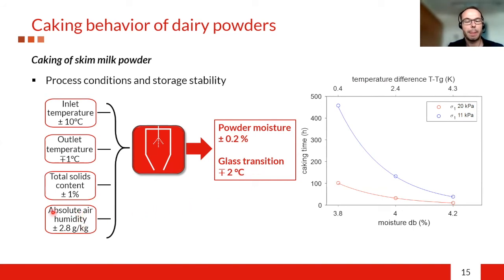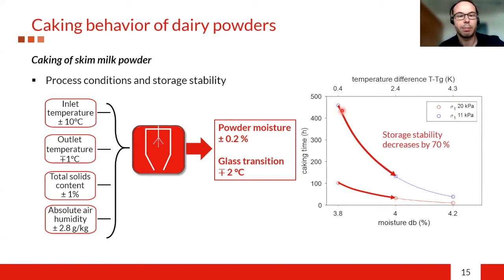Also the absolute humidity: an increase of 2.8 gram per kilogram in the inlet air of the spray dryer will increase the moisture content by 0.2. This can be the result of, for example, a rainy day during production. So this seems to be a very small change in the powder moisture content, but when you look at the storage stability, you can see that this has a dramatic effect. The storage stability decreases by 70% when you increase the powder moisture, because this changes the glass transition, and at a specific storage temperature you exceed the glass transition, so you have very low storage stability, and it is possible that the powder is caked after some storage time.